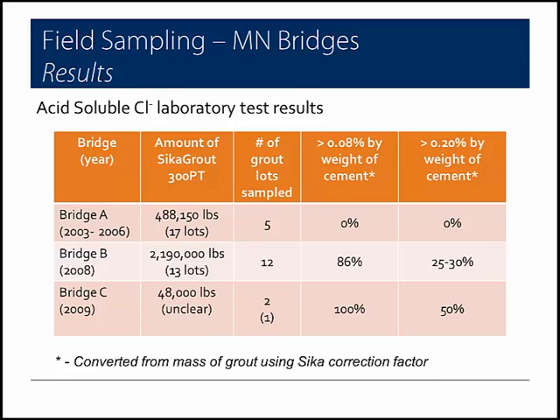We ended up getting 2 different grout lots, one that was at approximately 0.13% and one that was around 0.35%. So both exceeded the PTI specified limit. One exceeded 0.2% by weight of cement, but neither was the 0.5% grout lot that had been targeted. And in that case, for that particular structure, the difficulty in locating the grout lot was really related to the grouting records during construction and not the information from Sika. We know the grout lot is present in the bridge, but unfortunately there was insufficient detail in the grouting records to pinpoint exactly which tendons contain that grout lot.